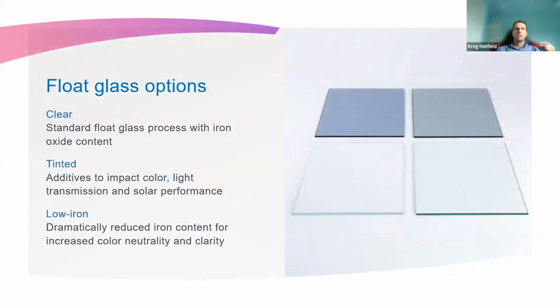So different tints or colors of glass. Obviously clear glass is the most commoditized product that we have in the market. We also have low iron. When we're making low iron, again, what we're doing inside there is taking the iron content out of the sand, and we're pulling that out of there and just making it a little bit clear. Normally from clear to low iron, you get about 2% higher visible light numbers with that. And then, you know, you would apply low E coating on there or however you want to put that on there. But again, you are pulling all the iron out of that glass to make it as clear as possible, more neutral.